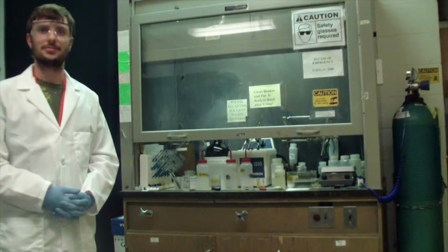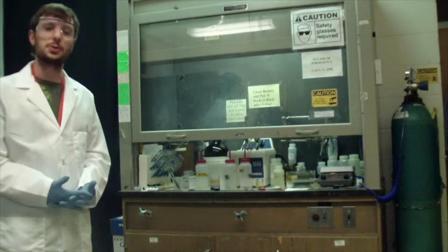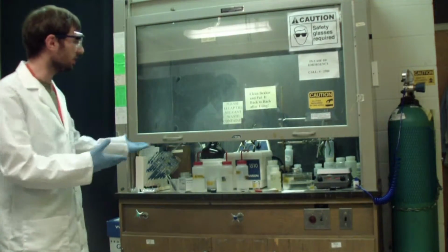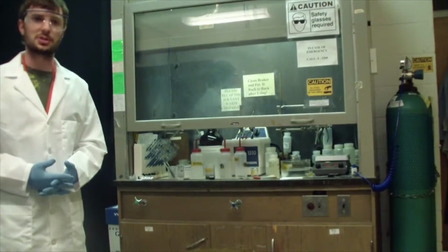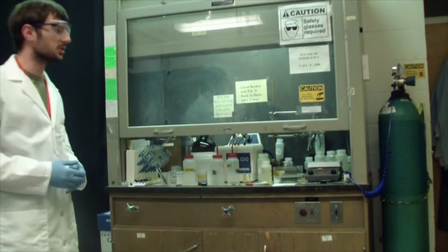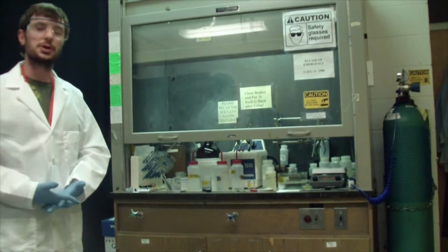Thank you very much. As you can see in this video, they're actually using solution chemistry in a lab-type environment to grow the graphene sheets onto these mini metal substrates. All right, so in nanotechnology, one thing that's very important is the purity of the samples. So mainly, we use a few routes to sonicate the samples in some kind of solvent. Before we grow the graphene in the furnace, we put them in acetone and we sonicate them for about 20 minutes